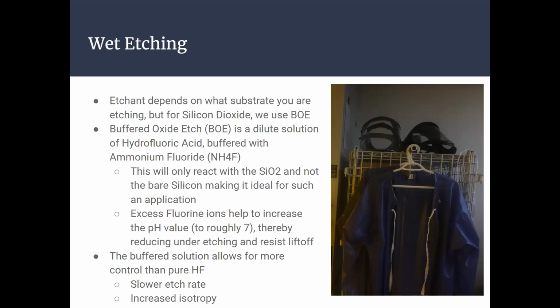But the benefit of doing this is that you get more controlled etching, and it makes sure that it truly acts isotropically, meaning attacking equally in all directions. And the other benefit of using hydrofluoric acid in particular is it only reacts with the SiO2 and it doesn't react with bare silicon. The process with SiO2 is much more favorable than Si, which means that it will basically always attack the oxide layer, and your pure substrate will be perfectly fine.